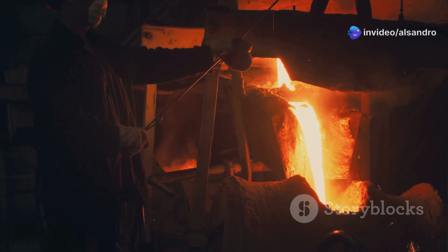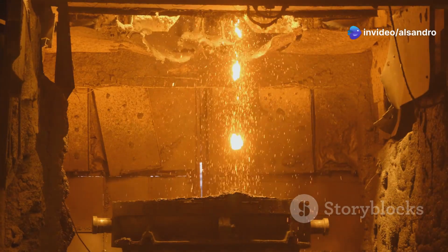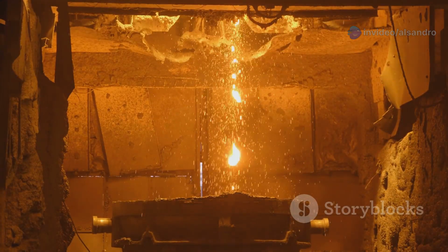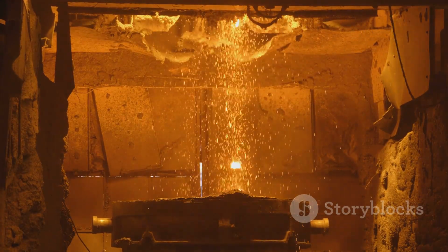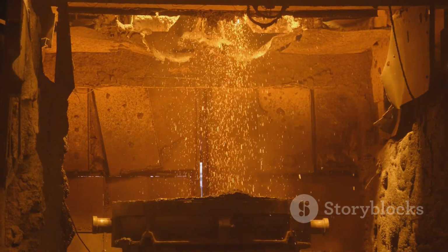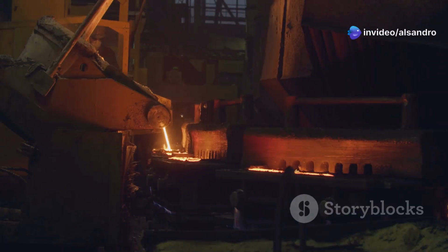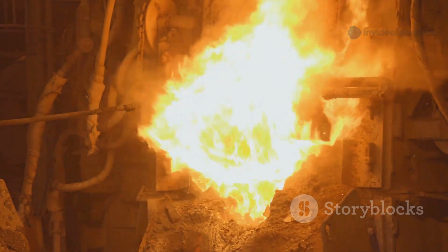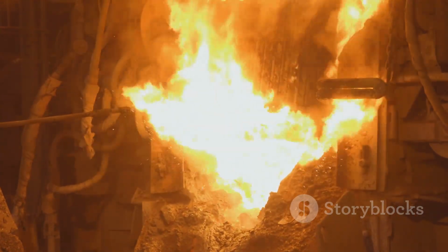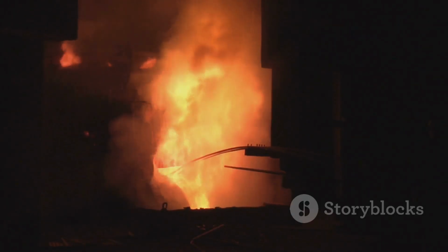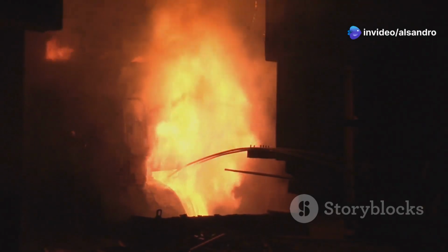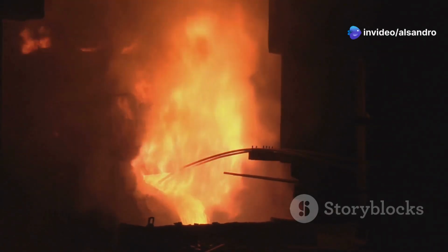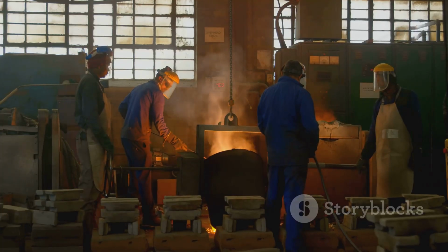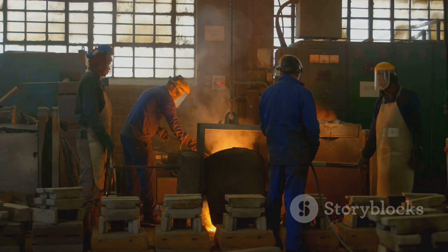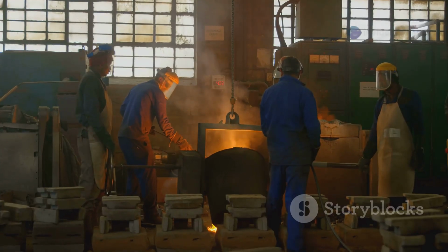Ultimately, the most dangerous effect is the risk of metal penetration. If the slag chemically erodes the refractory lining enough, it can create a weak spot. Hot liquid metal at thousands of degrees is relentless. It will find any crack or vulnerability. If it breaks through the refractory lining, it can reach the furnace's copper induction coil. The result is an explosive reaction between molten iron and the water-cooled coils. This is not just a myth, it's an extremely dangerous industrial accident that can destroy the furnace and pose a severe safety risk to everyone in the foundry. Managing slag isn't just about efficiency, it's about safety.